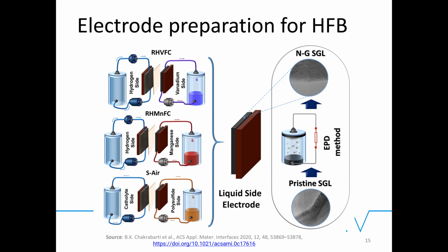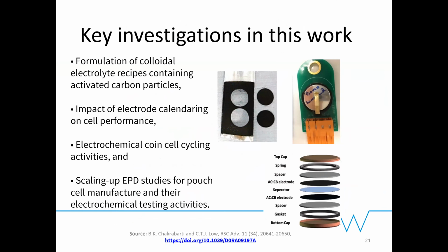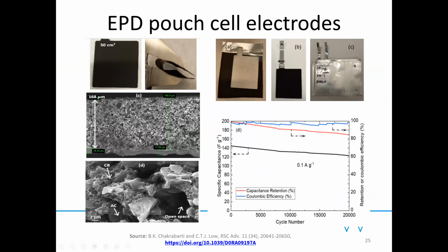Okay. Have you checked the particle size of your components with the results? Is there any direct relation with the particle sizes you use? Because there are different components, so it may affect the homogeneity, and you have some small holes, if I'm not mistaken, from your SEM results. Could it be because of the particle sizes too? You explained it as evaporation of acetone, but could there be another reason? Is there any relation between the particle sizes and the holes you observed in the SEM results?